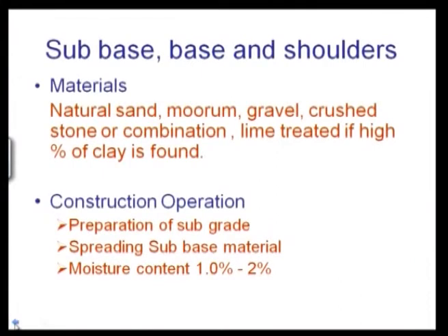Material for particularly subbase and base: natural sand, muram, gravel, crushed stone or combination of all, lime treated if high percentage of clay is found. Then construction operation: preparation of subgrade, then spreading subbase material, and moisture content generally maintained 1% to 2%.